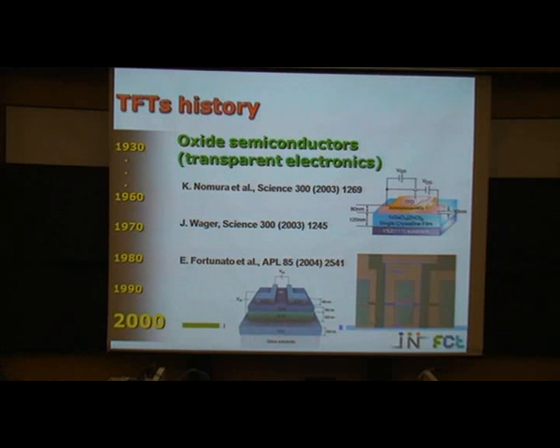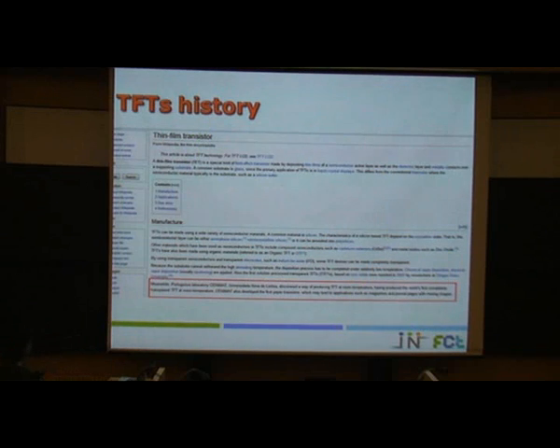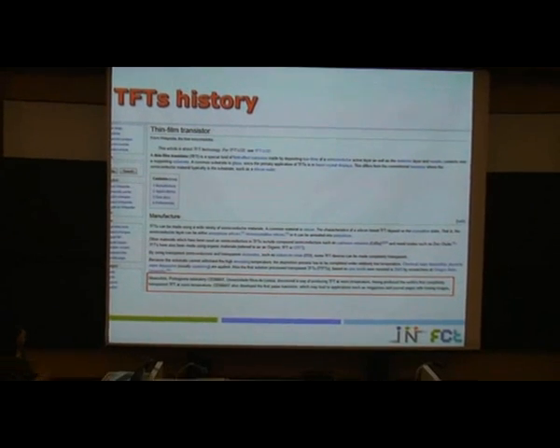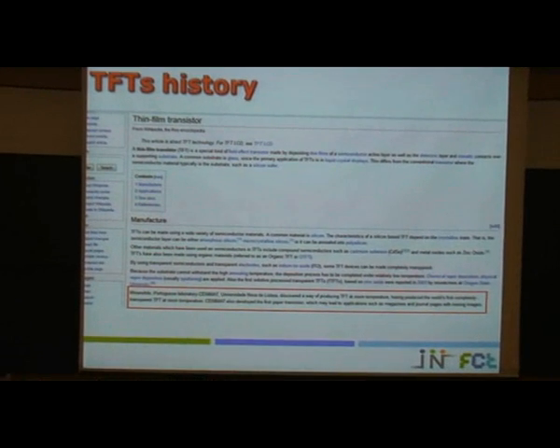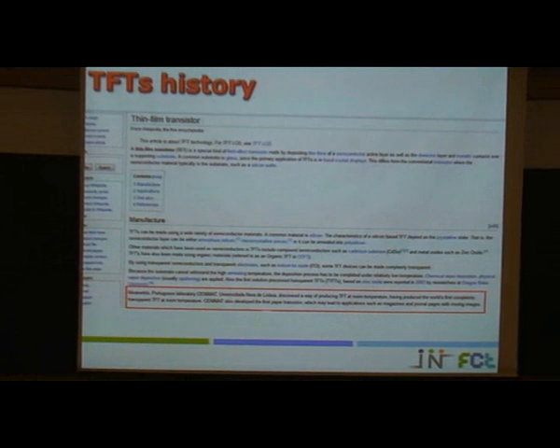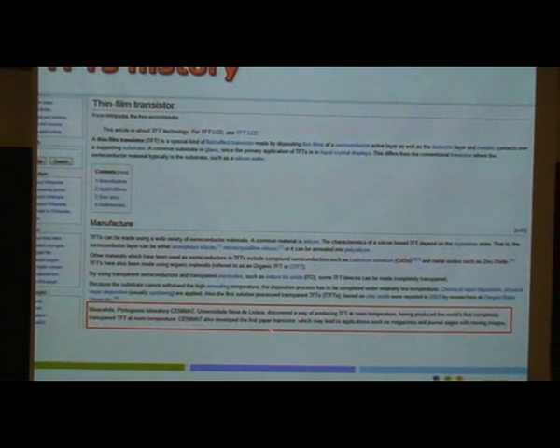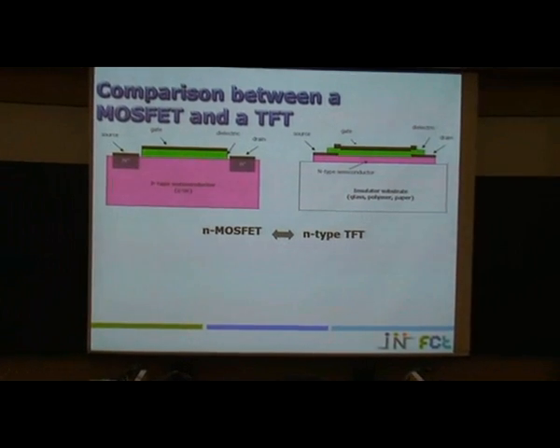So one year later, we proposed more or less the same. We use zinc oxide as the channel layer, but we grow this film at room temperature. So we produced for the first time in the world a fully transparent TFT at room temperature. And we are very happy because more or less two weeks ago we were preparing a book and a chapter for another book, and I was searching for TFTs, and I found on Wikipedia a report that a Portuguese laboratory also performed, not only the transparent TFT but also the paper transistor that we produced for the first time in the world. So we are very proud of our research.